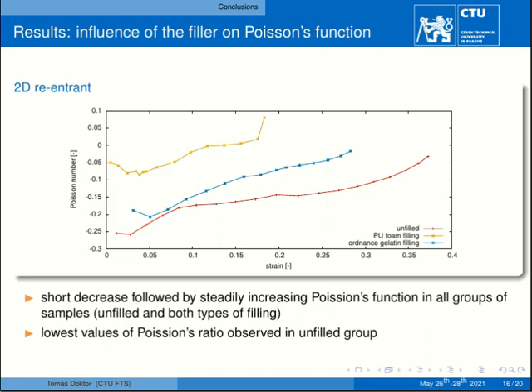Now to the core of the results of this investigation. While the filling exhibits a positive effect on energy absorption properties for all of the auxetic materials at tested strain rates, the auxetic behavior is suppressed due to the presence of non-auxetic material in the auxetic lattices, and the presence of the filling is a trade-off between the auxeticity and the enhanced energy absorption properties.